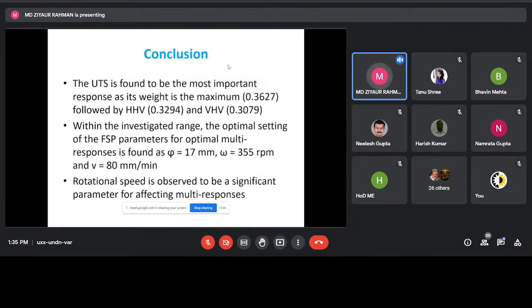The ultimate tensile strength is found to be the most important response, as its weight is maximum, 0.3627, followed by horizontal HV value and vertical HV value. Within the investigated range, the optimal setting of FSP parameters for the optimal multi responses is found to be 17 millimeter, 355 RPM and 80 millimeter per minute. The rotational speed is observed to be the most significant parameter for affecting multi responses. This is all from my side.